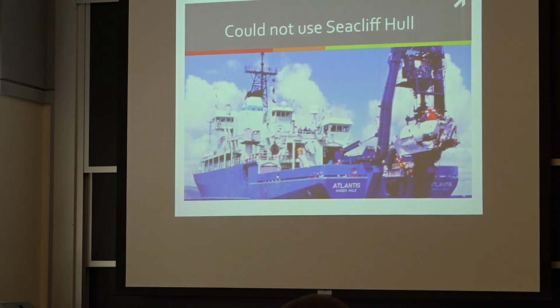We looked to see if, because the Navy had decommissioned the Sea Cliff, but they still had the titanium hull, which would have been good to use, except they couldn't, it was too heavy to put a Sea Cliff on top of the Atlantis. The Atlantis had only a 30,000 pound hoist capacity or something, and you had to have 40,000. They would have had to buy a new ship for $20 million, okay, or whatever. So we couldn't use the Sea Cliff.